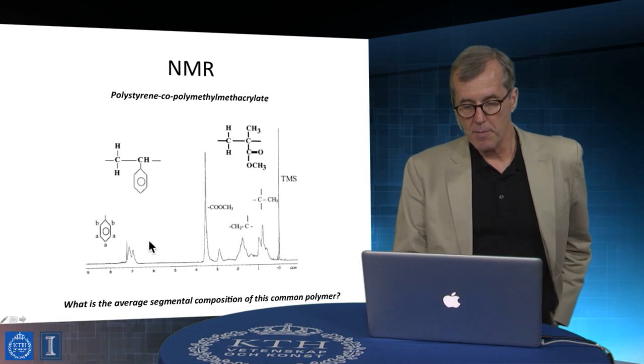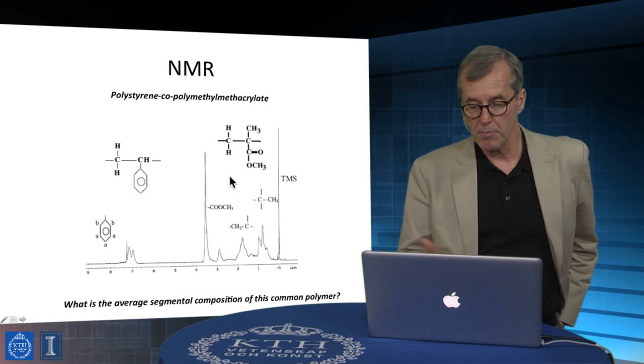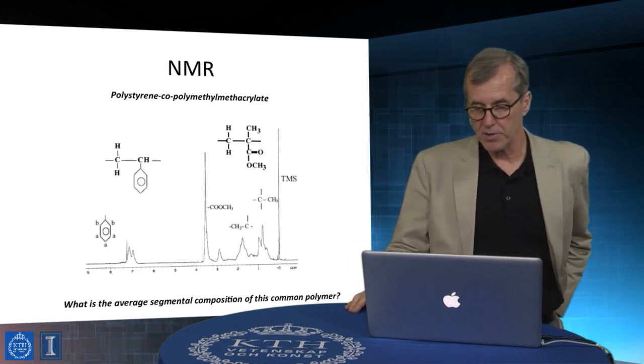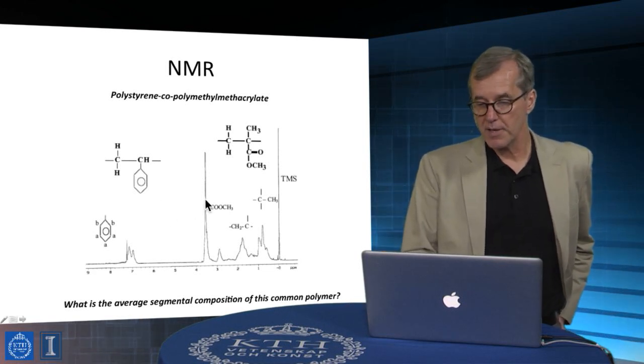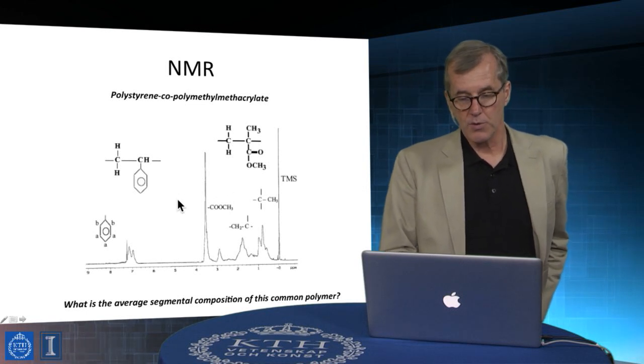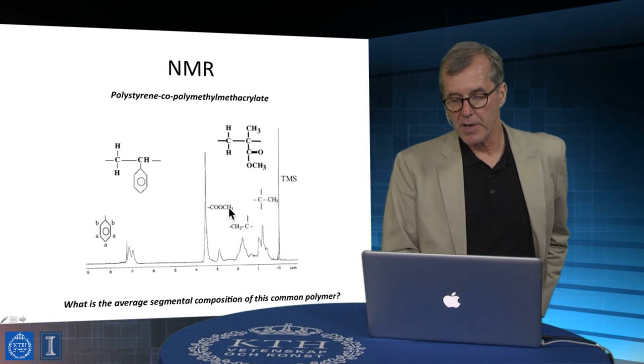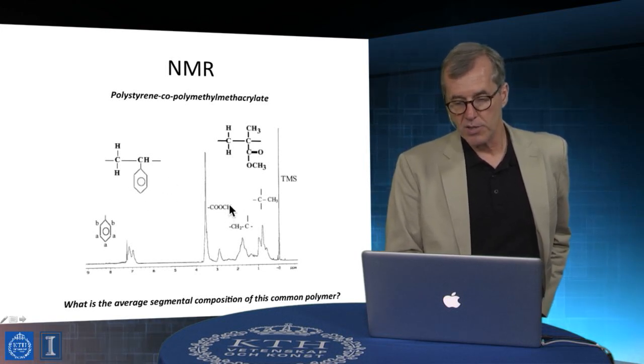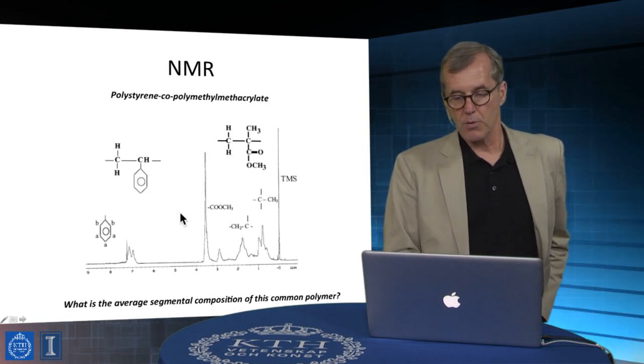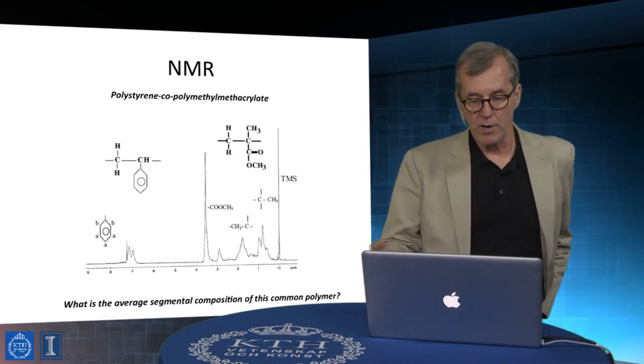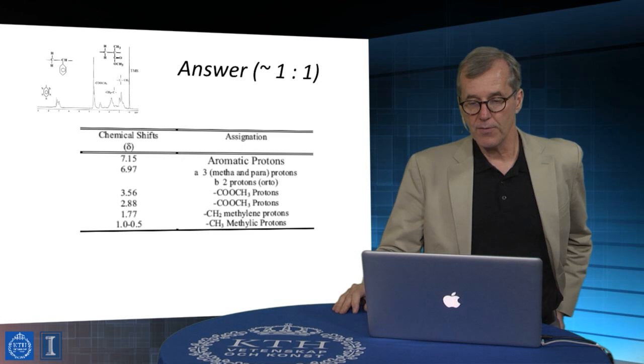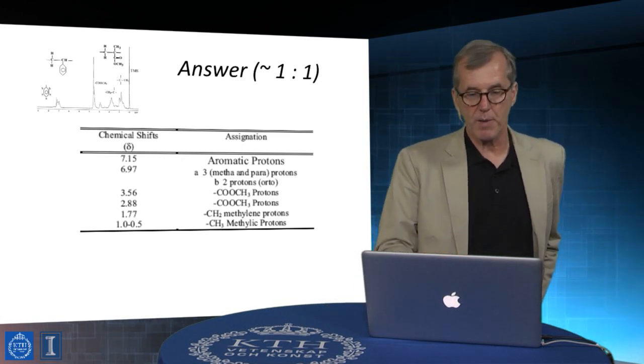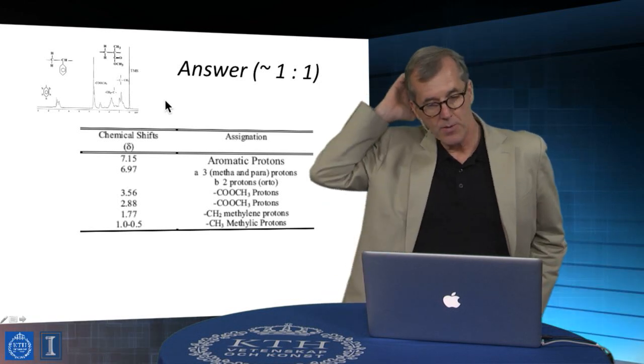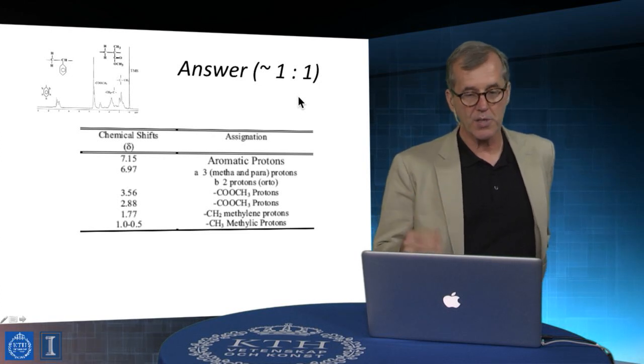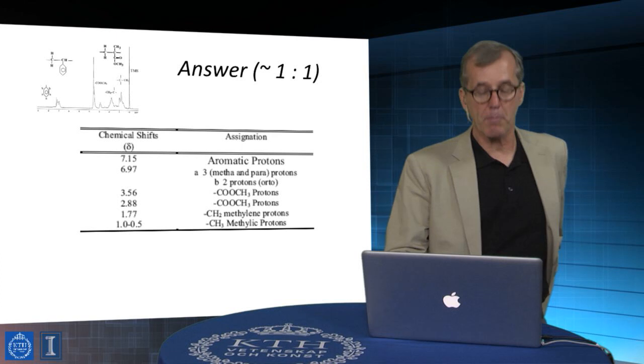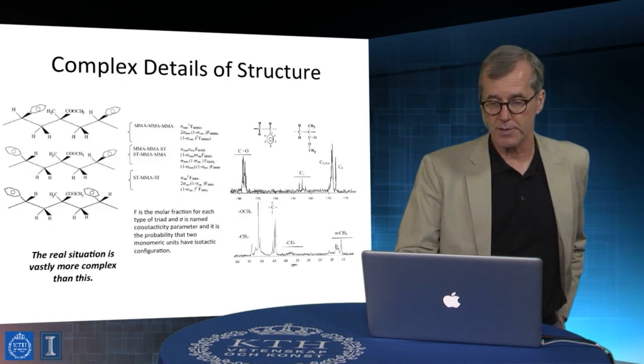Because it turns out that in NMR, the intensities of these peaks scale as the number of protons that are present. So this is a proton NMR spectrum. And if I integrate these intensities, I can then say how much of the two components there are. For example, here's the methoxy of this ester group, and here's the aromatic ring. This has 3, this has 5, and if you integrate this, you would then know very clearly how much of one versus the other you have. If you do the assignments of what's what in the spectra and integrate it, the answer is approximately 1-to-1. So yes, you can do that kind of assignment, and NMR is a very powerful way of doing that, right? Very precise.